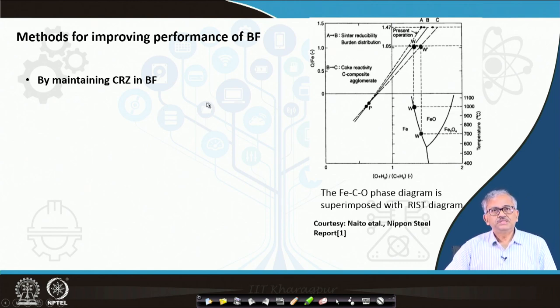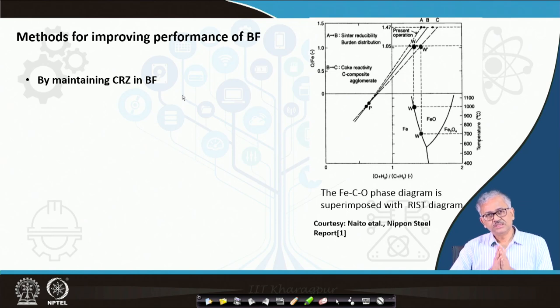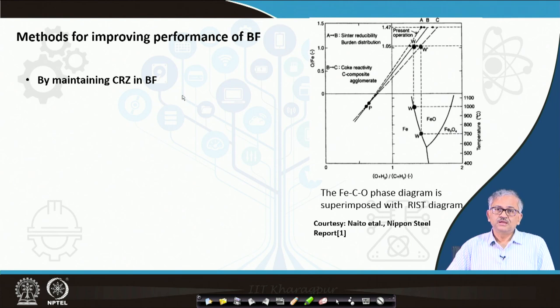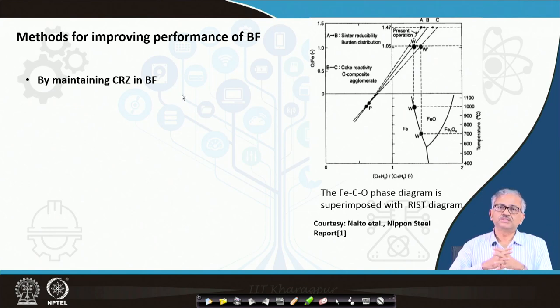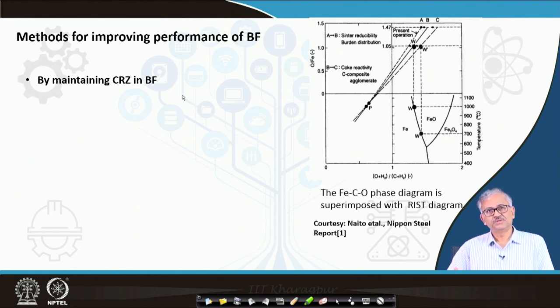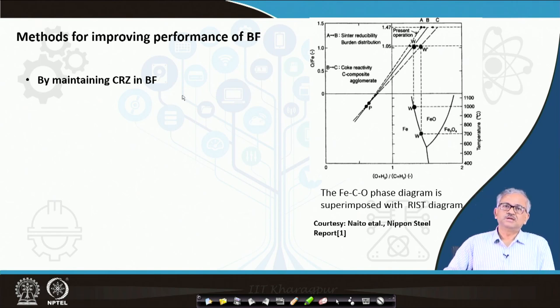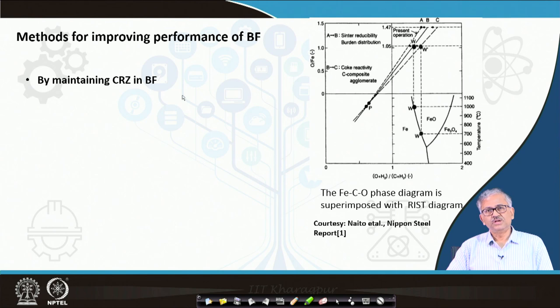By maintaining the chemical reserve zone in the blast furnace — which is very important — as previously discussed, there exists a chemical reserve zone on top of the isothermal zone. If you can maintain that, your CO utilization will obviously be higher. If your O/C ratio is higher, more CO is required; if you have much higher CO compared to what is required for equilibrium, then wustite reduction has very low CO utilization efficiency — about 70% CO remains at equilibrium. With a chemical reserve zone, 70% CO in the CO-CO2 mixture is at equilibrium, and that CO moving upward extracts oxygen from the higher oxides.